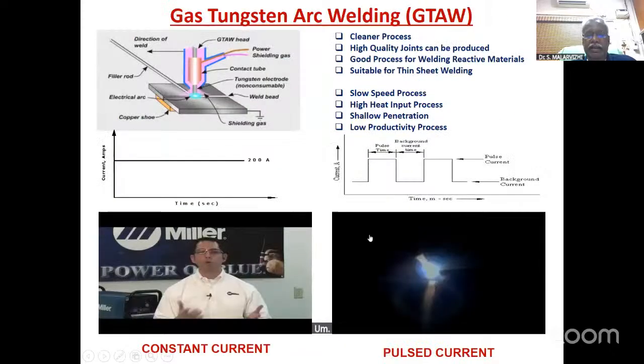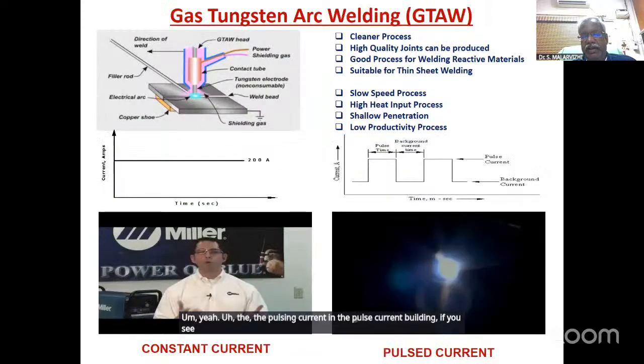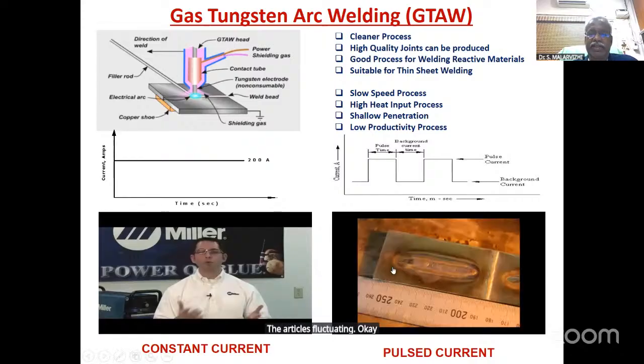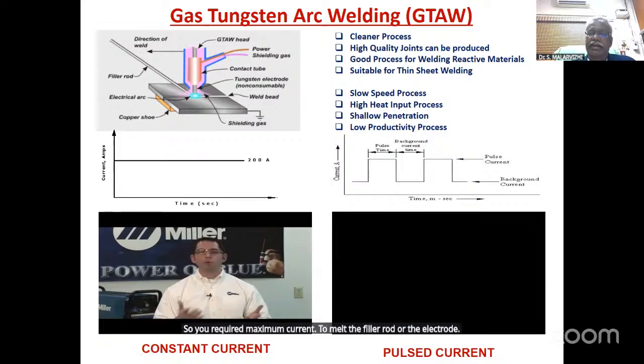So how does this pulsing current work? In pulse current welding, you see the arc is fluctuating. Why does it fluctuate? The current is varying from maximum current to minimum current. You require maximum current to melt the filler rod or the electrode. Once the molten droplet is formed and is transferred to the weld pool, which takes a few microseconds, the current can be reduced to a lower level. But you should not reduce it to zero, because if you bring the current to zero, the arc will extinguish. The arc should be maintained, while at the same time the current is reduced, and by reducing the current, the heat input can be reduced.